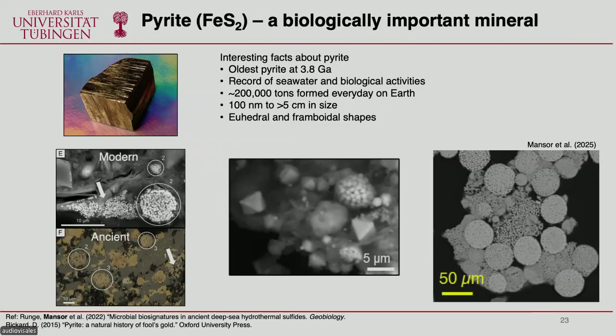The oldest pyrite has been found at about 3.8 billion years ago, which means that if you analyze trace metals, isotopic composition, and morphology of the pyrite, it may tell you something about the record of the seawater and biological activities. Pyrite is also forming actively today. It is estimated that about 200,000 tons per day is formed on Earth. They can have a range of sizes, going from very small to very big. And they also have very interesting morphologies. You see some of these pyrites are euhedral, with a cubic structure, but some of them have these framboidal structures where they are composed of microcrystals that aggregate together. And when you look at them under the microscope, it's really amazing because they're shiny and easily distinguished.